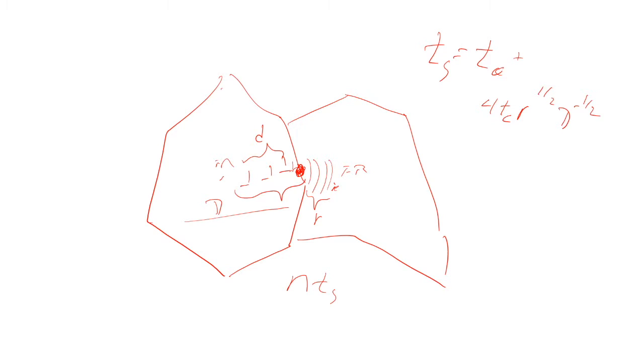And so this whole theory came up with, so Hall and Petch showed that for certain steel alloys, if they plotted it on a log-log plot, they got a slope that was pretty close to 1/2. And then everyone built a whole theory around trying to get that 1/2 exponent. But in reality, it's not exactly 1/2. It's somewhere in there, and the slope depends on the alloy. So these are all models.